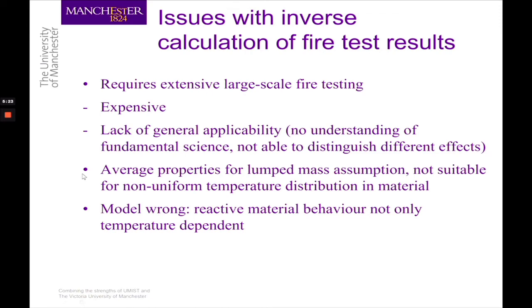The second problem is that it is based on this lumped mass assumption for calculating steel temperatures. So what we're getting from this method is an average value of thermal properties. And of course this makes it not suitable if you're doing more refined numerical modeling of temperatures, because you want to look into non-uniform temperature effects. It can also be a wrong model, because not all materials have thermal properties which are temperature dependent, especially with intumescent coatings, as I will explain to you. And intumescent coatings just happen to be, for now, the most common way of protecting steel structures.